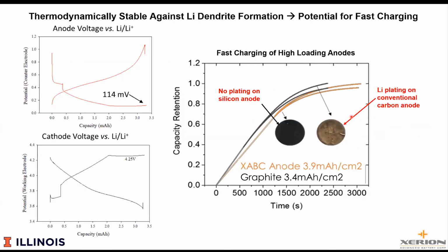And so now these are just some electrodes that we either we made or Xerion made. And this is a graphite and a silicon. They have the same loading. The silicon anode doesn't show any lithium dendrite formation. The conventional anode shows considerable lithium dendrite formation. And that's simply because in the conventional anode, we simply couldn't get the lithium in quickly enough, and so it plates on the surface.